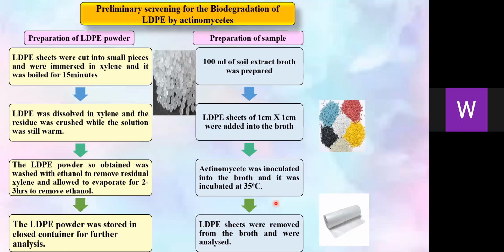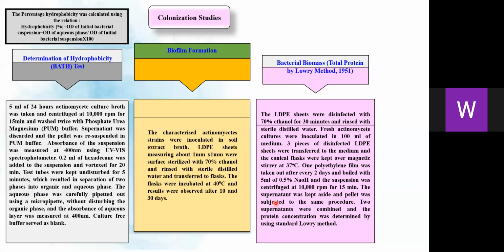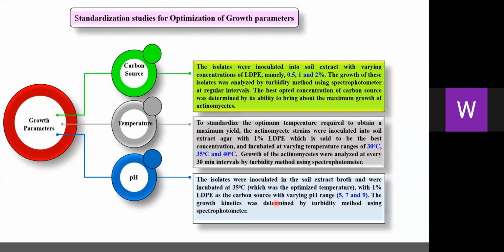Colonization studies were done by determination of hydrophobicity by the bath test, biofilm formation, and bacterial biomass by Lowry method. Next, standardization studies for optimization of growth parameters. The growth parameters were standardized for better growth of the actinomycetes, like temperature, carbon source, and pH. Carbon source of a varied range of 0.5, 1 and 2, temperature of 30, 35 and 40, and pH of 5, 7 and 9 were assessed and optimized by the turbidity method.